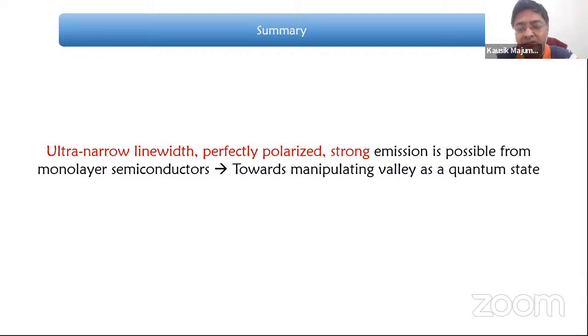So what happens is that, at least what we see in our lab, the lifetimes of these interlayer excitons are significantly larger, in the order of, let's say, nanoseconds to hundreds of nanoseconds, right? So they have many things to do in those hundreds of nanoseconds, right? It's fairly uncontrolled. So my guess is that, like I showed in the data, it might be a little difficult to maintain polarization because of this. But having said that, I must also say that because the electron and hole are residing in two different layers, their overlap is relatively less. So your exchange is going to be less. So we have to just do it and see, probably.